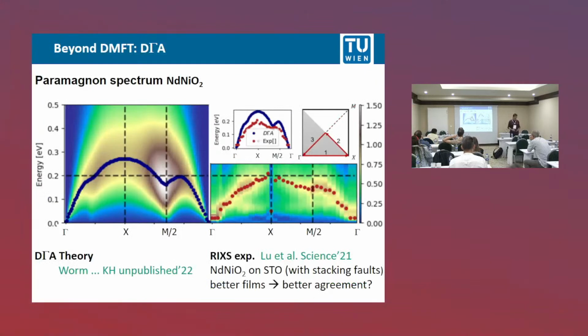Okay, that was the superconducting TC. It's driven by antiferromagnetic fluctuations, so let's compare the antiferromagnetic fluctuations to experiment. We can compare to RIXS. That is our paramagnon spectrum, so energy-momentum resolved, and that is the paramagnon excitation in theory, and that is the experiment. So again, no parameter fitting, it is just our old data, and we now also calculated the paramagnon